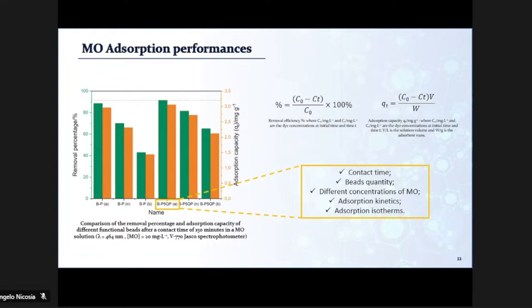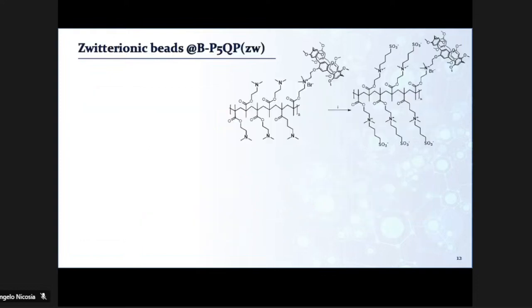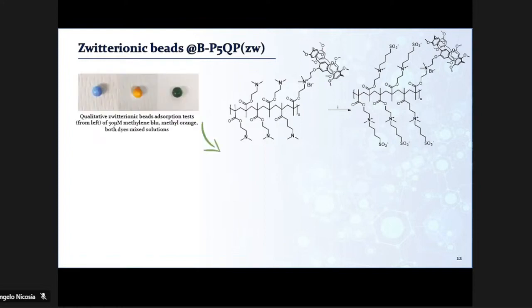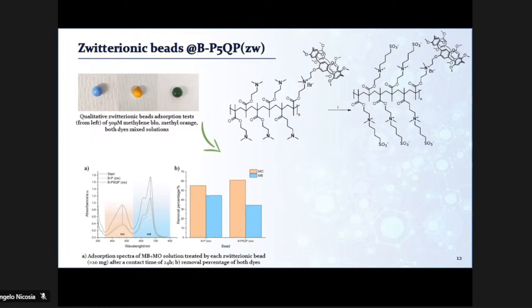So for these systems, we studied the effect of the time, the quantity, different concentrations of methyl orange to understand the absorption kinetics and the absorption isotherms and the models that better define its behavior. We went deeper and studied the post-functionalization of these beads, employing 1,4-butane sultone to obtain a zwitterionic bead. This zwitterionic bead is able to retain both anionic and cationic dyes, and it's able also to be regenerated, but we did just the first preliminary tests on this.